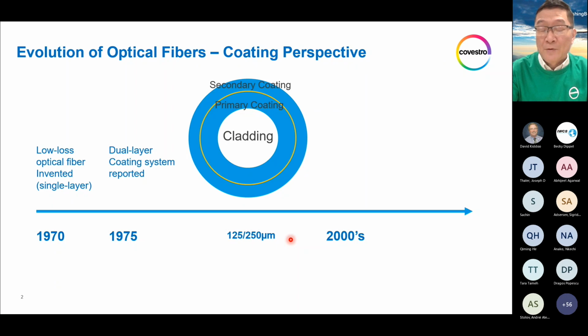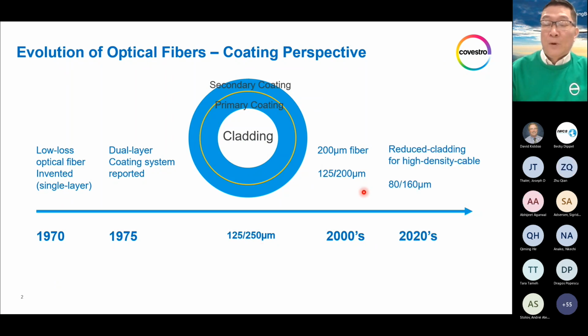Fast forward to around 2000, that is when a reduced fiber size called 200 micron fiber came about. That actually means we still have 125 micron in the glass cladding size, but we reduce the overall coating thickness. So the overall outer diameter of the coated optical fiber is only 200 micron versus 250 for the last few decades. The reason is for high density cable, we want to fit more fibers in the same size of a cable, because in a lot of big cities, we have limited space to put a cable in the ground.